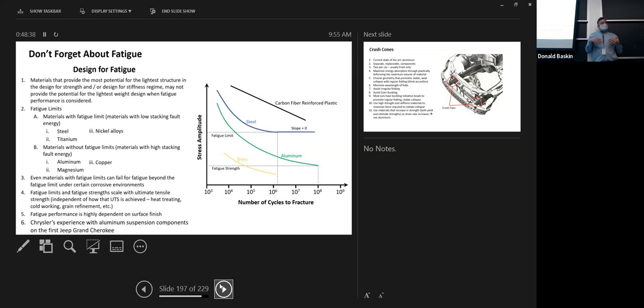And they had failures during testing. They had to keep adding aluminum back in order to get the stress low enough so the part would go a decent number of cycles. They kept doing this over and over again. Basically, they were back to the way the cast iron went. That had a lot to do with the fact that they weren't using very high quality castings, and they didn't understand the aluminum they were using and how to make it clean. But just keep this in mind: when you're designing things, it's not only stress, it's fatigue too.